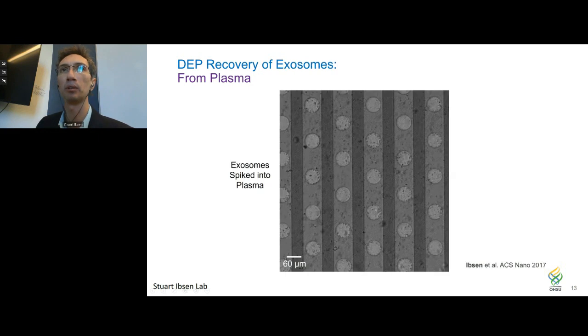And so that's exactly what we were able to do. So we were able to get a glioblastoma, a brain cancer cell line, and we collected the exosomes that were produced by those cells, and we labeled them red so that we can follow them through this entire collection process. We spiked those exosomes into a human plasma sample and then put them on the chip here. And you can see we're looking down at the surface of the chip. Each circle is an electrode in the array.